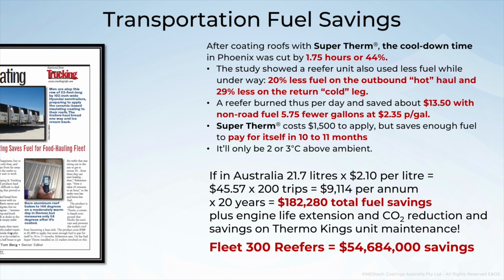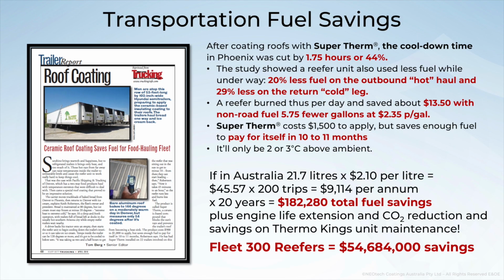One of the interesting tests we did was on reefer trailers running between Phoenix and Denver. After Supertherm was applied on the reefer containers, there was instantly a cool down time of 1.75 hours, which is 44% faster. There was 20% less fuel used on the outbound or the hot haul and 29% less on the cold leg. So they've actually saved more money on the colder run than they have on the warmer run because the cooling doesn't need to work as hard.